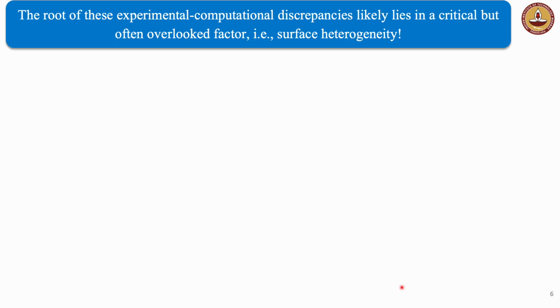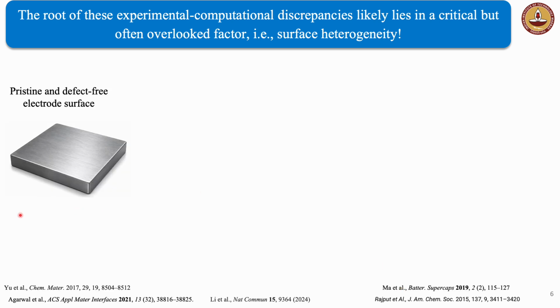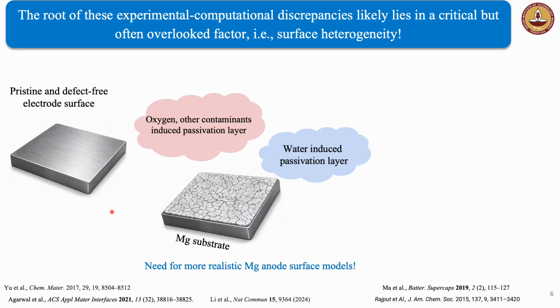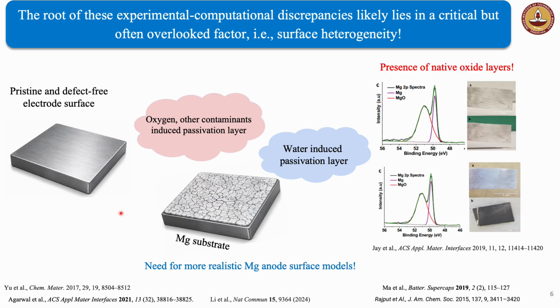The root of these experimental-computational discrepancies likely lies in a critical but often overlooked factor, that is, surface heterogeneity. In theory, we often model electrode surfaces that are pristine and defect-free. But in reality, magnesium anode surfaces are never pristine, but feature native oxides, passivation, defects, and contaminants, which persist even under carefully controlled conditions. Indeed, experimental studies have shown the presence of native oxide layers that could not be removed even after polishing.